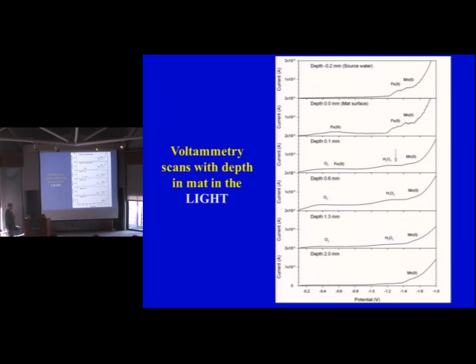So what you see is a water-mat interface. The loss of iron-2 is where you get the oxygen production. Notice that there's the manganese signal, but not the iron signal. Notice peroxide is almost on top of the iron-2, and we're starting to see a little bit of a bump for iron-3. We have to blow these up. This is just the full scan, just to give you an idea of what they look like. Manganese is still present as you go deeper. And then, if I go back, you'll notice that once you get through that maximum part of the mat, now you're getting back to a manganese and an iron signal, and you're losing the oxygen. So that's how you saw that oxygen profile.